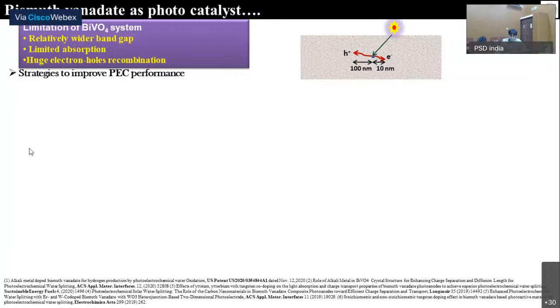In a typical bismuth vanadate system, when the light falls and a charge pair generates, the electron moves only 10 nanometer, whereas the holes are able to move only up to 100 nanometer. So if we keep the thickness of the film less than 100 nanometer, then only can we efficiently separate them. But if we keep the thickness less, in that case, we will lose the absorption efficiency. We cannot utilize the whole light which is falling on the surface.